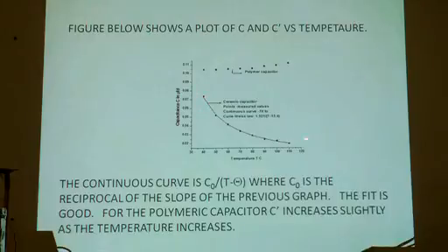This shows how the capacitance varies with temperature for the ceramic capacitor and how the capacitance varies with temperature for the polymer capacitor. The continuous curve shows the Curie Weiss fit with C naught equal to 1 by slope of the straight line and theta 13.4 degrees. You see that the continuous curve fits the experimental data very well, showing that the capacitance obeys this Curie Weiss equation. It is 1.921 by T minus 13.4 microfarad.